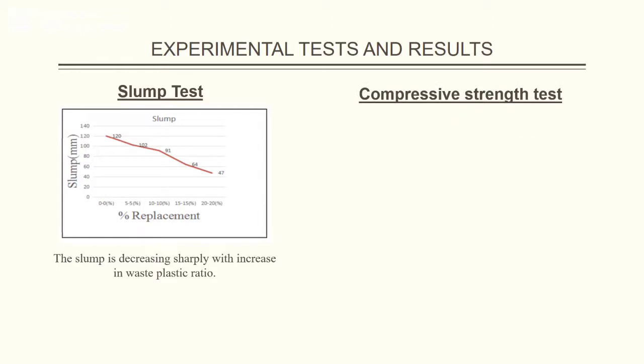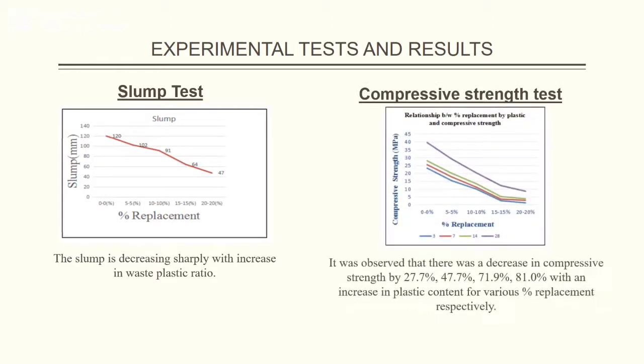Compressive strength test. This is used to determine the compressive force or the crush resistance of a material and the ability of the material to recover after a specified compressive force is applied and even held over a period of time. It was observed that there was a decrease in compressive strength by 27.7%, 47.7%, 71.9% and 81% with an increase in plastic content for various percentage replacements respectively.